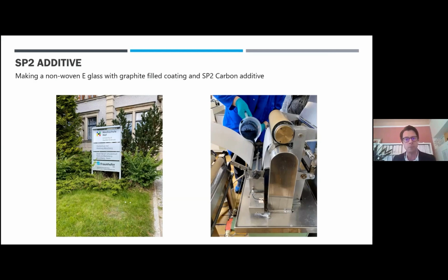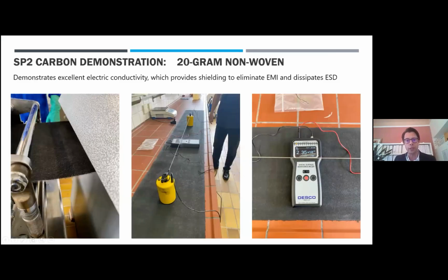Next page, please. And we end up impregnating, curing it. And what you see here in the middle is basically we ended up with a graphene coated e-glass surface veil that is allowing us to give conductivity. You see the measurement with our test setup, and you can also see that we have been significantly reducing resistivity and bringing conductivity to a surface veil, which then can be used or replaced in any laminate being built up. So we have a balance: we can bring in the graphene additive or a high concentration of additive at the surface through the resin. We can bring it to the surface plus a surface veil.